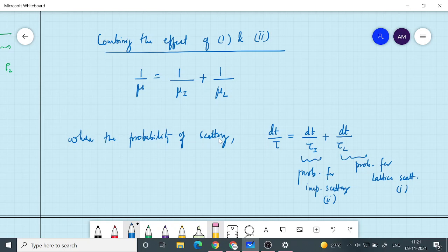Because the mobility expression, you remember, was q tau divided by m star. So this was our expression. So tau is the parameter through which mobility becomes dependent on these scattering mechanisms, where m star is a constant that basically comes from the band structure that we derived. But one of the main reasons for electrons having higher mobility than holes is the m star, the effective mass of electron and effective mass of holes. If you compare, whichever is lesser will have higher mobility. Effective mass of electrons is normally lesser than the effective mass of holes.